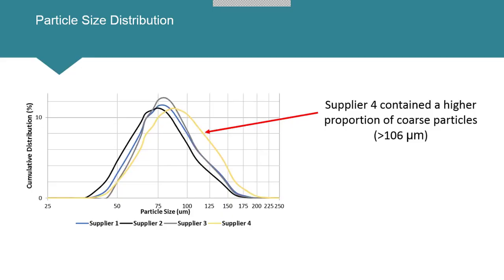Next, we want to look at something like particle size. So generally speaking, there are multiple methods that you would use to measure particle size. So you would use sieve analysis combined with something like a laser diffraction. This graph shows some results from a laser diffraction methodology. Some of the things we would be typically looking for is adherence to that size fraction. So does the bulk of the distribution lie in 45 to 106? Is my material monomodally distributed, like all 4 are in this case? Is it Gaussianly distributed? Again, all 4 are.